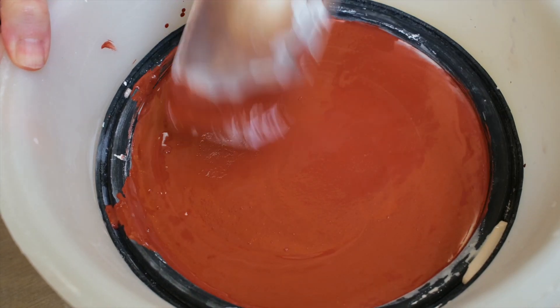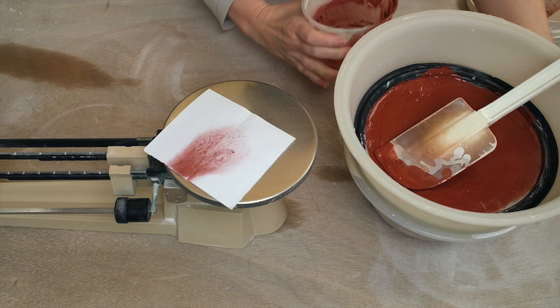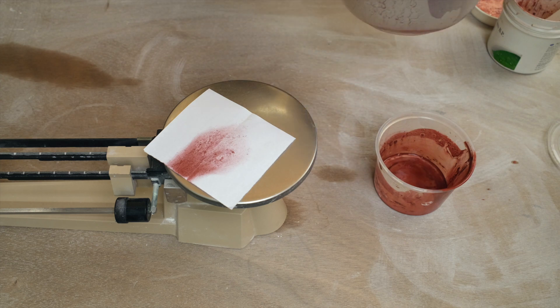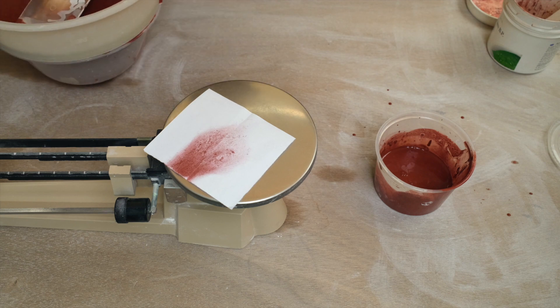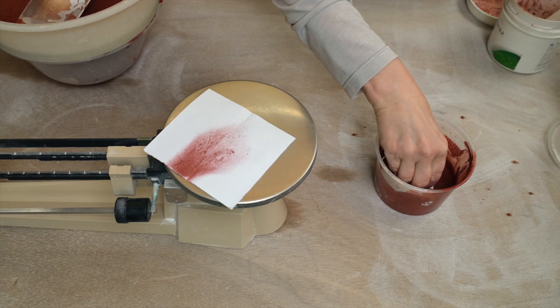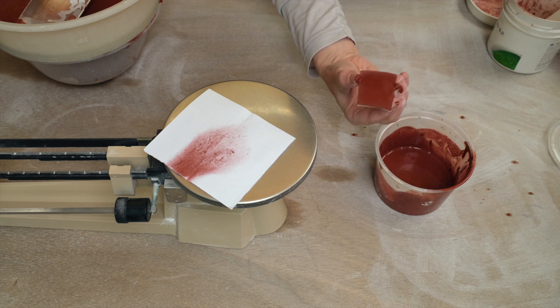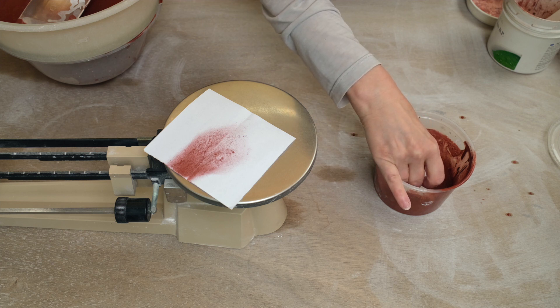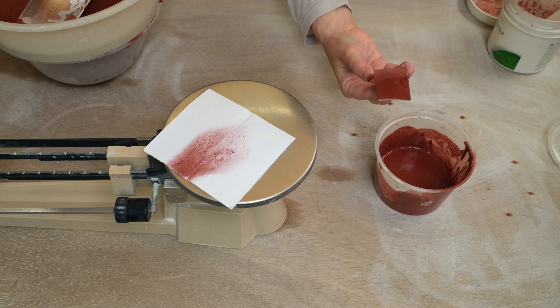This is such a lovely red colour, but eventually it's going to be fired to a sort of dark brown-black colour. Then I'm going to dip another test tile into this glaze — it has both iron oxide and cobalt carbonate in it: 10% iron oxide and 1.5% cobalt carbonate. I'll dip the test tile twice. Iron oxide glazes take a long time to dry on the tile, so you have to wait until it's dry before you can handle it.